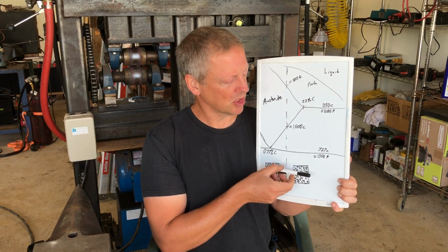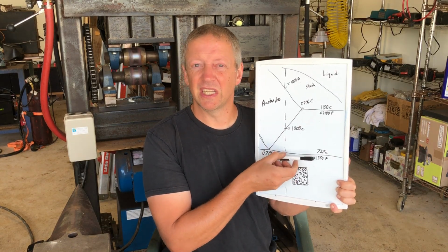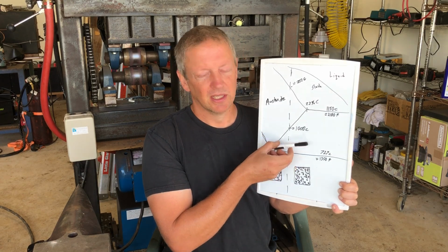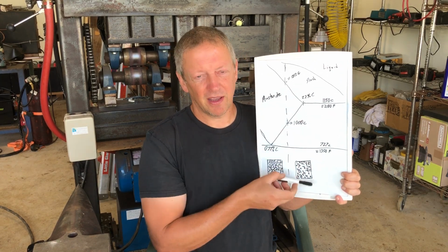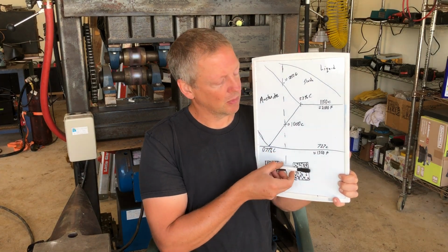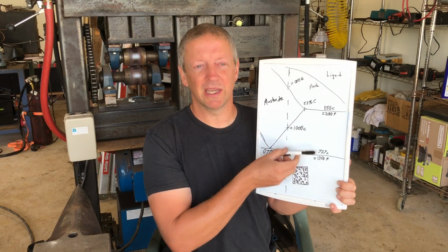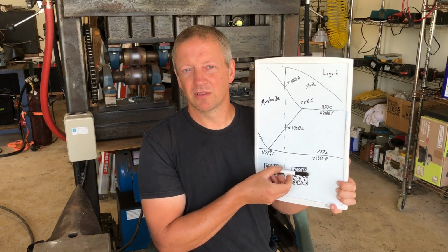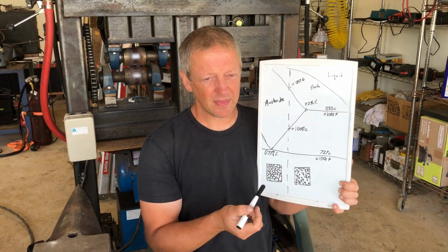So with really slow cooling, or very slow heating, critical is right where it shows it to be here. Same thing, very slow cooling, critical is right there. The faster you're cooling, the more this line moves. So when you're forging, especially on a thin blade, cooling's pretty quick. Subcritical is further down, or the critical line is further down than you think it is.